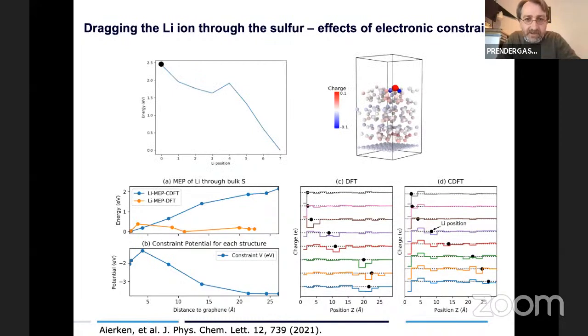Sorry for the bad animation here, but this is just an example to show very quickly. So as I move the lithium ion down through the system towards the graphene, what you'll notice is that if I do that just with regular density functional theory, the effective energy of each of those positions is almost the same. And the reason for that is that the electron is moving with the lithium ion. It's basically in the sulfur around the lithium at each point. I can't prevent that from happening.